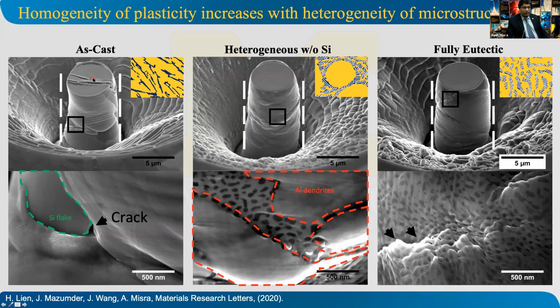so this was not laser refined, showed these brittle cracks that form during compression, and right at the point of silicon flake where aluminum is plastically deforming but silicon is not, and that leads to the failure. But under heterogeneous or fully eutectic structure, especially fully eutectic, you see signs of more uniform deformation.